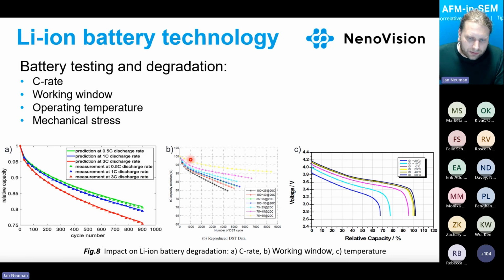The other thing which influences the degradation of batteries is the working window. If we cycle the battery in the full range from 0 to 100%, the degradation will be much faster compared to cycling in a not so deep range, for example, from 65 to 75%, as you can see on the yellow curve. And the other thing which influences the properties of the battery is temperature.